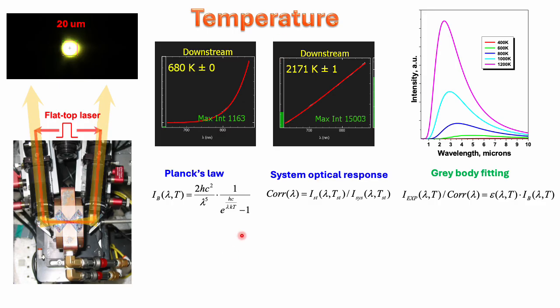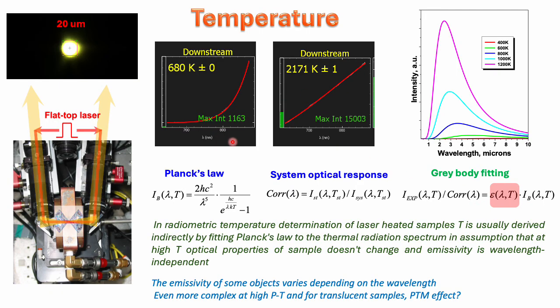It is very important to know the temperature of the material during laser heating in a diamond anvil cell. Usually what we can do is fit thermal radiation with a Planck distribution. Of course, if you have a very good system optical response, we can fit the gray body, fitting the emissivity and the temperature, and get a very nice fit. But we typically assume that emissivity doesn't change with wavelength and temperature.